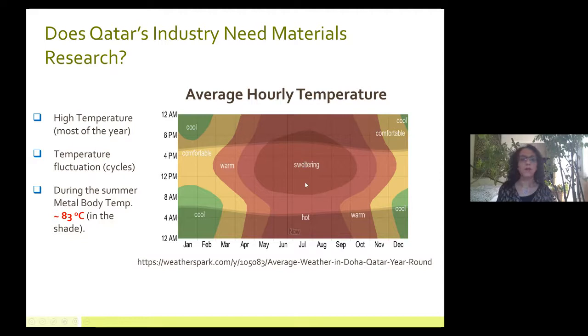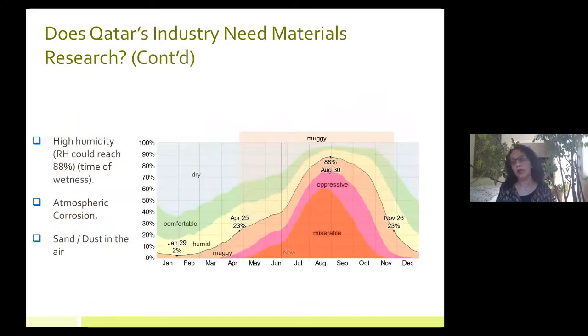So if you measure the metal body temperature, when you consider the radiant heat, it's around 83 degrees. That's what we measured in the field when we are in the shade. So you can imagine that it gets very high for metals. And these cycles of temperature create a problem because the metal starts suffering from stress due to these cycles of temperature. The other problem we have in the environmental conditions that we have in Qatar is the humidity.